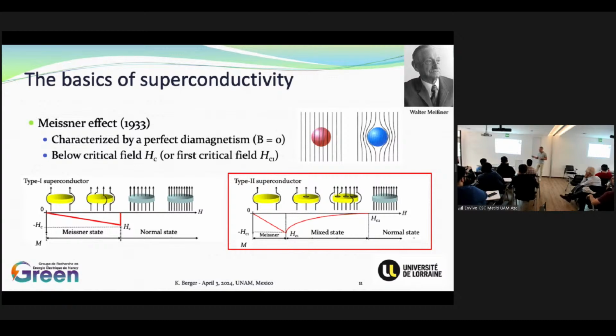So you can see here when the superconductor is warm, the field crosses the superconductor. Just by cooling down the sample, the field is expelled from the superconductor. So this is exactly the opposite of what we have with ferromagnetic material. With ferromagnetic material, you are focusing the magnetic field. With a superconductor, you are shielding. But in fact, you can have almost the same applications with this effect as with iron, because you can produce a variation of magnetic field in that case. But this effect is not very strong.